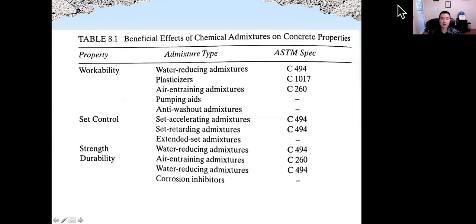So this table summarizes the beneficial effect of chemical admixtures on properties of concrete. Okay. So for workability, we can use water reducing agent, plasticizer, or so-called superplasticizer. That is another name for high range water reducing agent. Okay. Air entraining agent can also help the workability of concrete. Okay. For set controlling purposes, we could have an accelerator, which reduces the setting time by increasing the chemical reaction in concrete, or we could have a set retarding agent which slows down the hydration, okay, increasing the setting time of concrete.